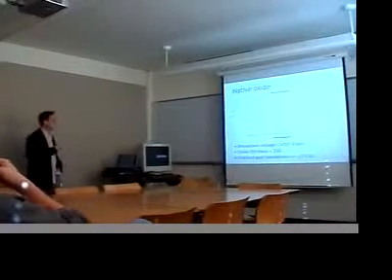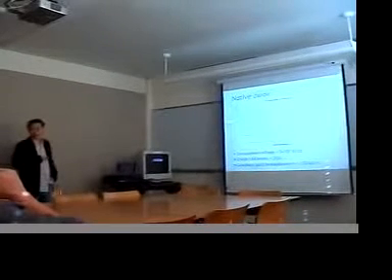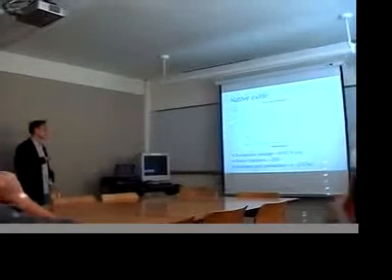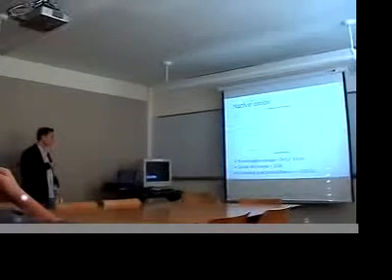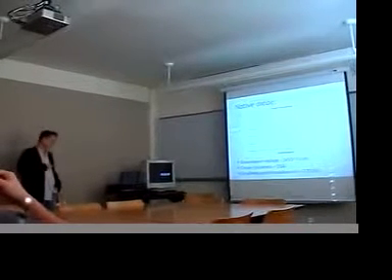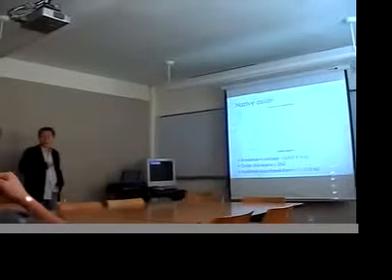And so we only thought about native oxide very recently. So we did this. As you can see, we apply a voltage from 0 to 10. The previous graphs that you've seen are only from negative 1 to 1 because we don't want to burn out the carbon nanotubes. But this time we did, because we want to really see whether there's an oxide. So I think this is very clear evidence that we do have some stuff at the contact. As you can see, there's a breakdown voltage over here. If you do some reverse engineering, this will give you around 20 angstrom, a little bit high, but I think that's still reasonable. And if you extrapolate this, take this gradient, this will give you around 270 kilo ohms, which is in line with most of our devices where we actually observe ohmic contact.